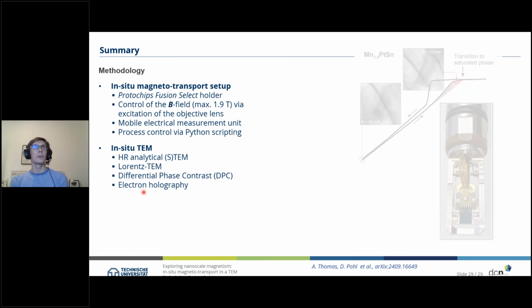I showed to you that we came up with a new in-situ magneto-transport setup using the Protochips Fusion Select holder and our TEM, applying fields up to 1.9 Tesla using the excitation of the objective lens. Using different electrical measurement units and Python scripting, we were able to automate the whole measurement process, and had at the same time access to the whole capability of our TEM, like analytical TEM, Lorentz TEM, DPC, even electron holography.